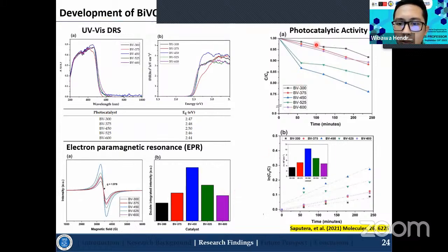And if we have a look through the photocatalytic activity performance, we can see that it mimics the defect generation as illustrated from the electron paramagnetic resonance characterizations, where the BV 450 degrees C gives the best performance compared with other types of the catalyst. So indicating that there is a correlation between the defects once again, and also the photocatalytic performance of this catalyst. And in the below figures, we also calculate the rate constants based on the pseudo first order kinetics, and it confirmed this trend with the defect generation as illustrated from the EPR measurement.